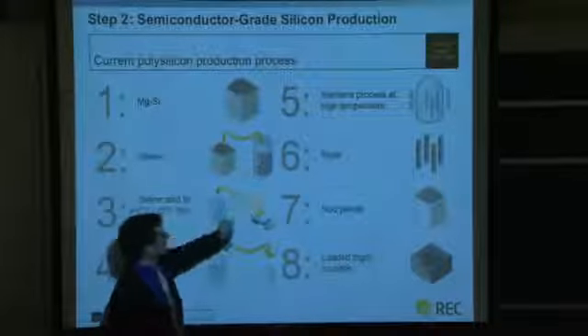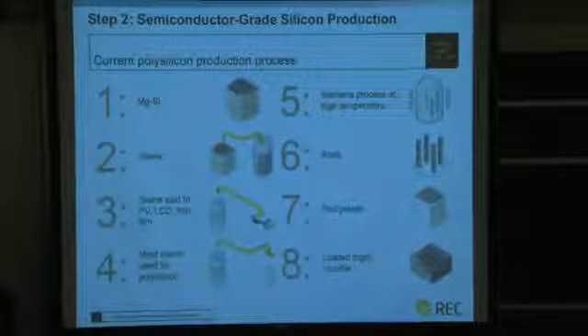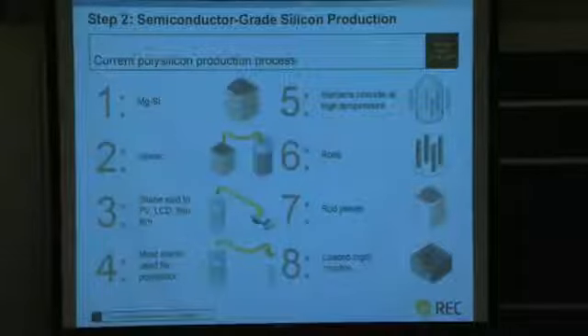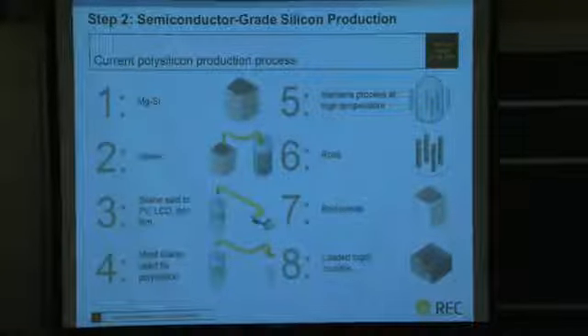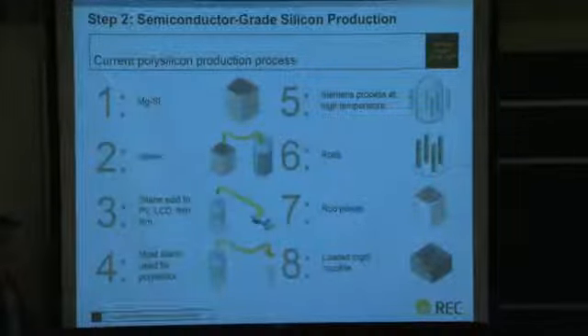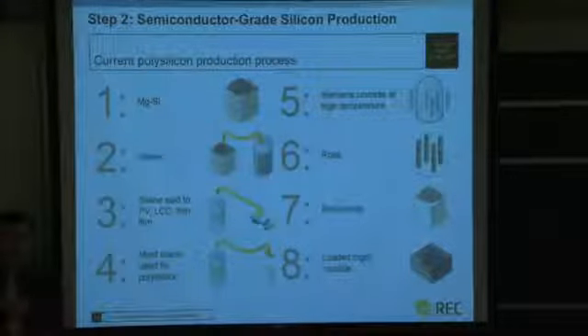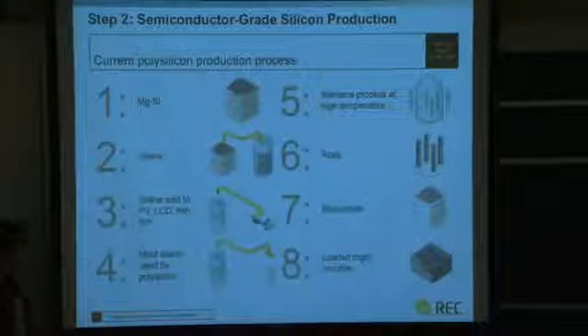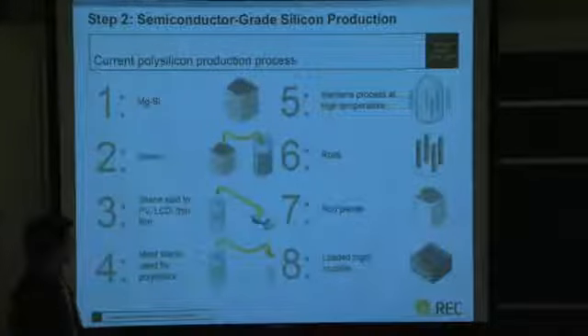And that's what happens in this step right here. We're gasifying the silicon. To extract the pure silane gas, it's the distillation process that's used. Large towers, similar to fractional distillation, where we might heat up the material, and then depending on its mass, it settles down to a certain height within that tower, and we're able to extract it.